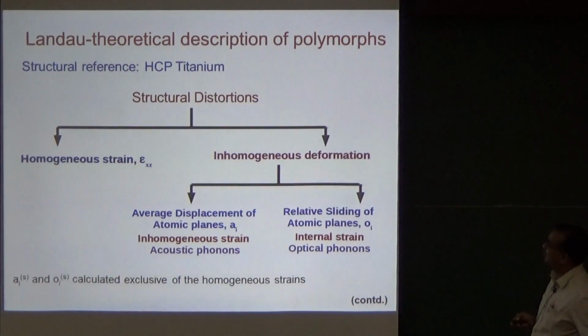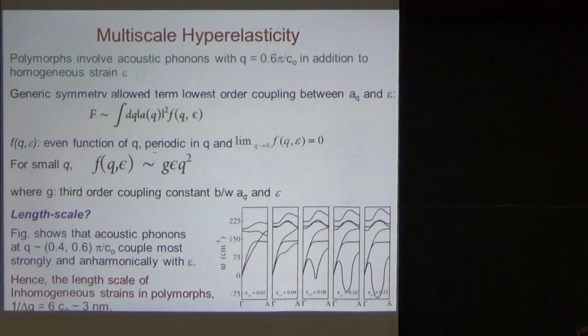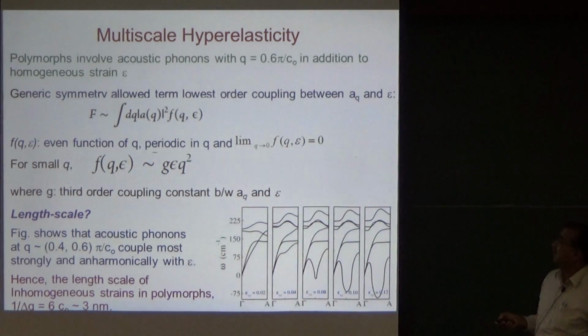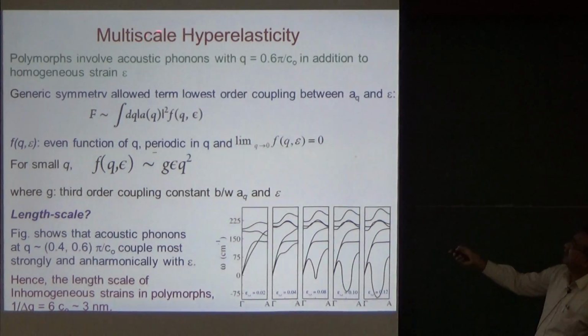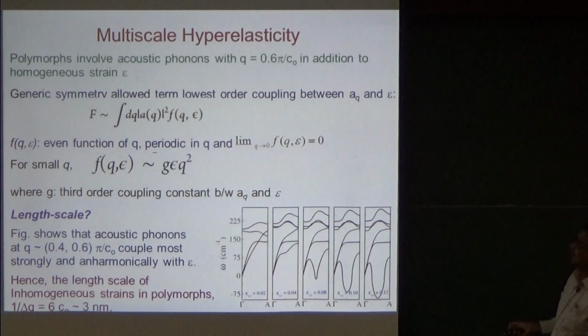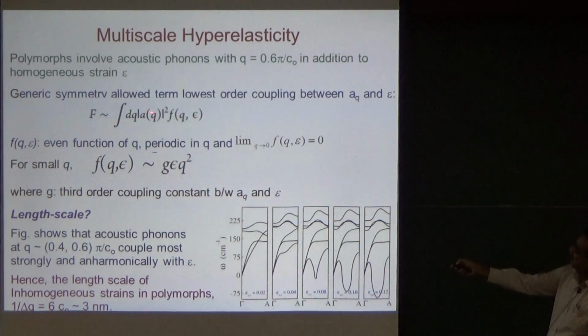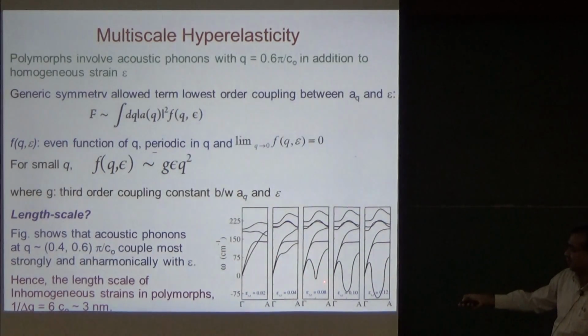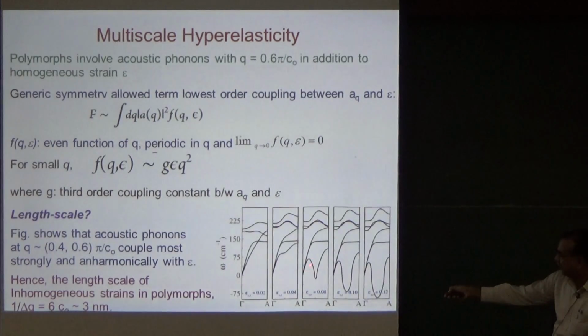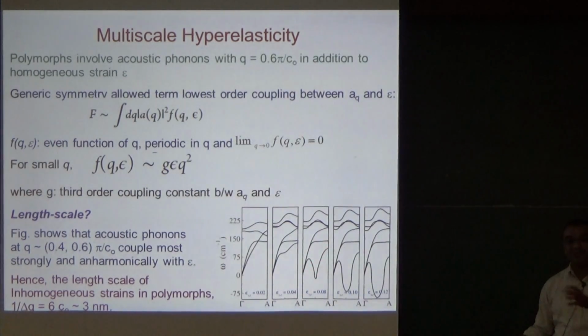Okay, so I'll close my talk by summarizing that the mechanism that we found for nanoscale ductility of HCP metals involves what we termed as multiscale nonlinear elasticity or hyperelasticity. So typically, you write down a generic free energy function in terms of acoustic phonons like this, and strain is basically given by the wave vector times acoustic phonon, and if you expand it, you have to have nonlinear terms, which gives you instabilities in the acoustic phonon branch. You see, we are applying shear strain here, 0.02, 0.04, 0.12, and you develop an instability in the acoustic phonon branch, and that's what gives you the stabilized polymorphic forms, which are inhomogeneously ordered.